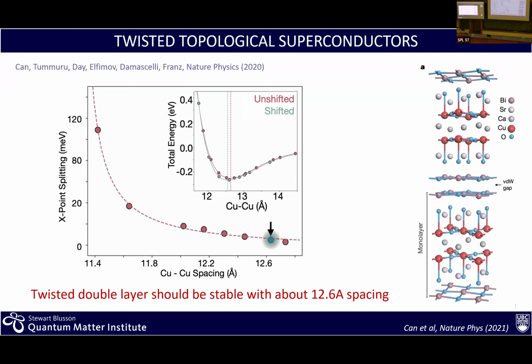So the calculation is now done, assuming that we can break the material here. We know we can. We bring them back in the calculation. We rotate by 45 degrees. And then here we look at the total energy of this bilayer and ask, where does the total energy reach a minimum? And the minimum is here for 12.7 angstrom between the middle of these layers. And then we can look at this quantity. This quantity is a splitting in the band structure, but basically it means a splitting between electronic levels. If the two layers are very close, the splitting between the electronic levels in the structure becomes very large. Now we look at the value where we are, 12.7, and this is what defines the interaction. And it happens that that parameter is right in the range that you need to have a dx squared minus y squared plus i dxy superconductor. So it's the right parameter value in order to get a topological superconductor in this case.